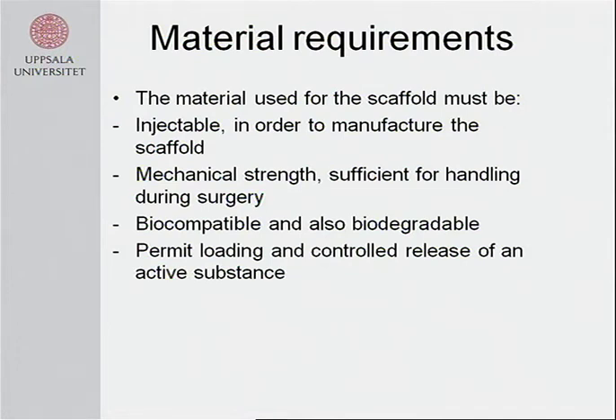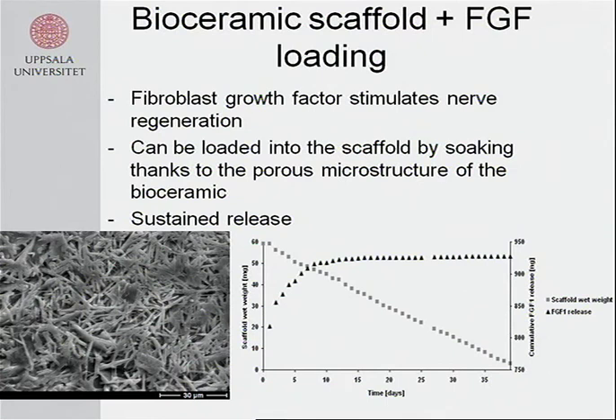So, since I'm a bioceramics person, we have worked with a bioceramic strategy for this. And we load the scaffold with FGF. And we get a slow release of the FGF as the scaffold is resorbed. And it's resorbed after around 5 to 6 weeks in vivo.